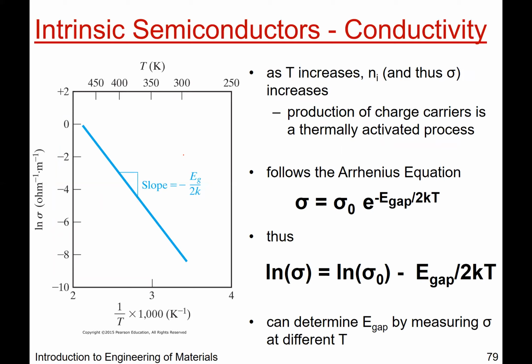Okay, so there you have it. We've done this type of problem before where we can calculate what the energy term is by taking the natural log of both sides and basically solving a system of equations to get, before we had vacancy formation energy, we also calculated diffusivity values. Now we can calculate band gap as well, and it all rests on the Arrhenius relationship.